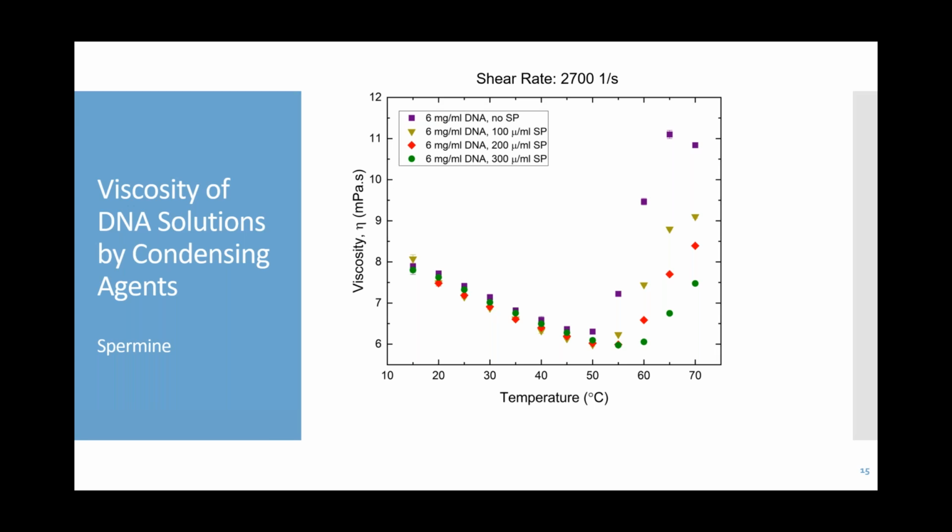So at melting temperature, some of the hydrogen bonded double helix separate, I mean the hydrogen bonding disrupts partially and not entirely, so that many more crosslinks are formed than are possible, and then the adjacent molecules start to cross-link together, and this increase in cross-linking leads to an increase in viscosity, which is clear in this plot. Also, with increasing spermine concentration, melting or denaturation temperature shifts to higher temperatures.